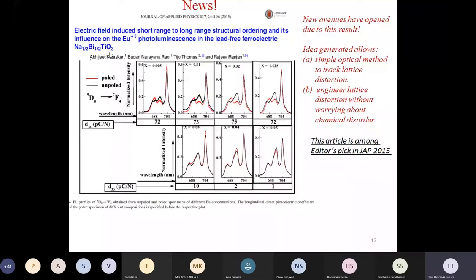So you can actually put certain luminophores and excite these materials. And not only that, what is interesting is that which came out in this paper, wherein using electric field, we were able to overcome some of the optical losses that come about otherwise due to crystal defects. So there is some kind of a compensation that you can actually work with.